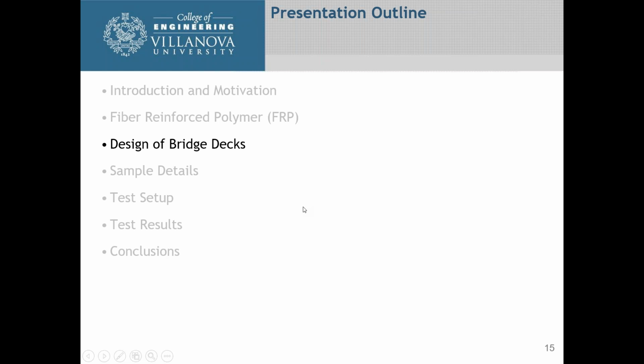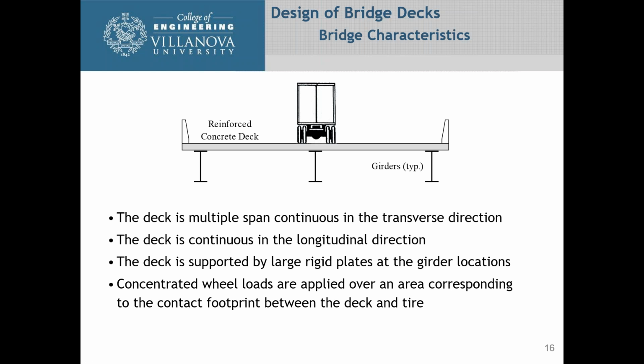So the next thing we want to look at is how do we design the bridge decks. A bridge deck is reinforced concrete, and it is a multiple span continuous in the transverse direction. In the longitudinal direction, the deck is one continuous plate. So really the deck is supported by large rigid plates at the deck girder locations, which are the top flanges of the plate girders. Then you have concentrated wheel loads applied over an area corresponding to the footprint between the deck and the tire. And this is clearly indicated in AASHTO, an area that's 20 inches by 10 inches.